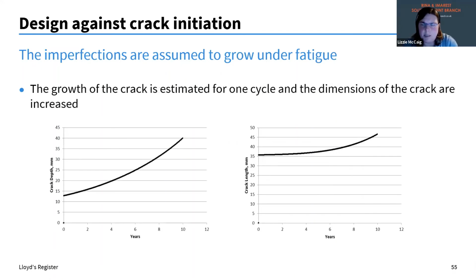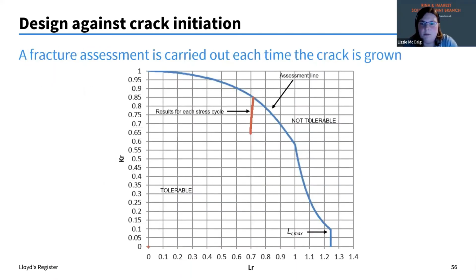And so for each cycle that the ship goes through, the load cycle, you estimate the growth of the crack and you increase the dimensions of it, and then you test it again to see whether it will fracture. So you carry out this fracture assessment every time the crack's grown. And basically, if it's above this blue line, then that is not tolerable. And if it's below this blue line, then it's a tolerable defect size and you can keep going.